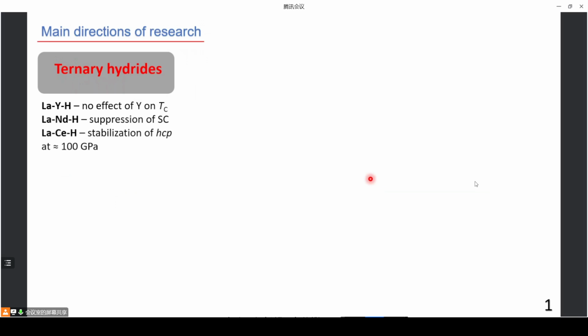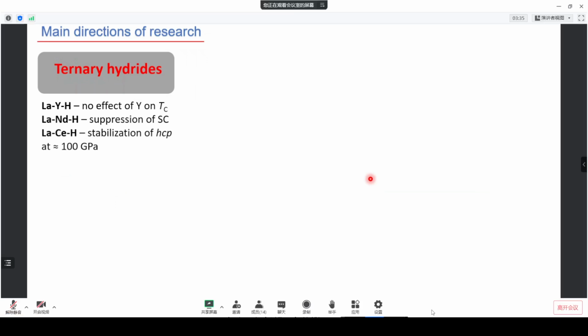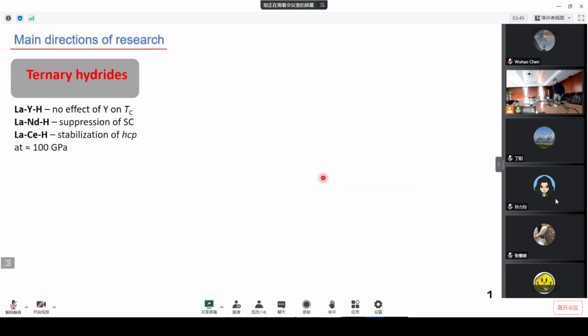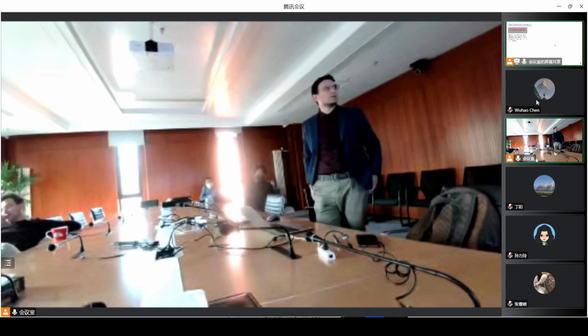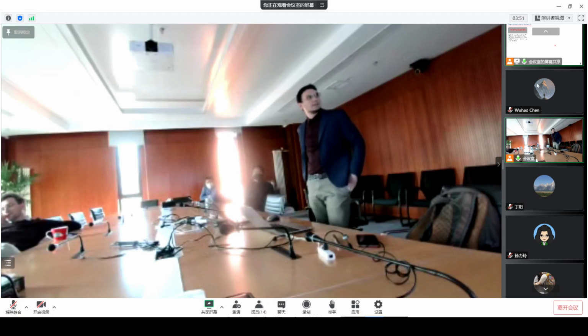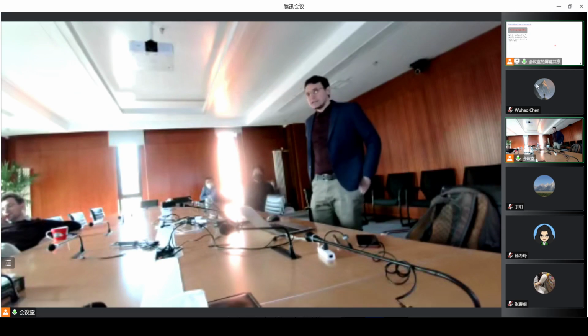The fourth direction is a synthesis and search for high temperature superconductivity in ternary hydrides. At this moment, 3 systems were investigated and published: lanthanum-yttrium hydrides, lanthanum-neodymium hydrogen system, and lanthanum-cerium hydrogen system. 2 groups from Jilin University published recent papers about this nice system. So what can I say about this?